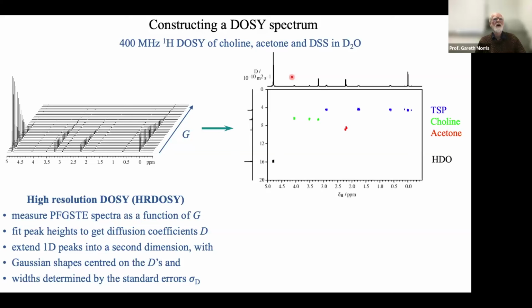But notice the bit at the bottom here. We put our peaks in the diffusion domain where the diffusion coefficient D belongs, but they have widths. They have uncertainty. If we have completely random errors, then we have a Gaussian distribution of probabilities of where the peak should be.